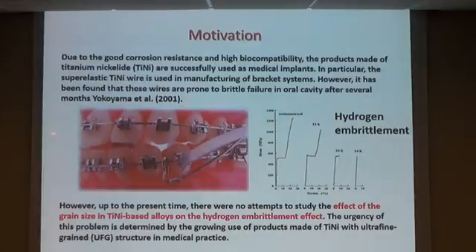It is a bracket device with titanium nickelide wires with superelastic properties. Superelastic titanium nickelide wire is used in manufacturing bracket systems. However, it has been found that wires are prone to brittle fracture in the oral cavity after several months. The origin of this effect is hydrogen embrittlement.